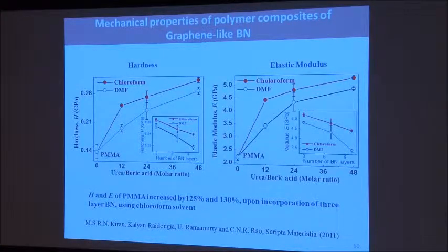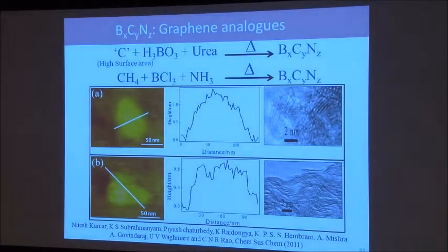People dump a lot of boron nitride into polymers, but that is not the way to do it. What you have to do is make single layer or 2-layer, put a small amount of it, and that is enough. The smaller the number of layers, the better it is for strengthening composites. So these are some of the things on boron nitride. One minute on this material.